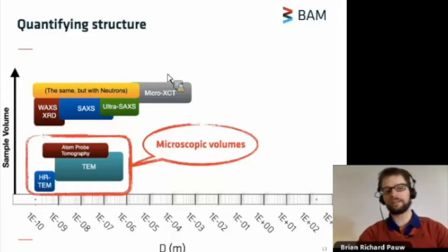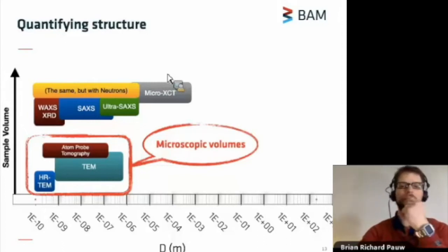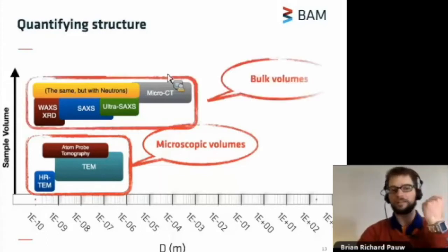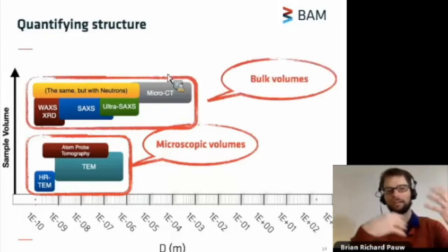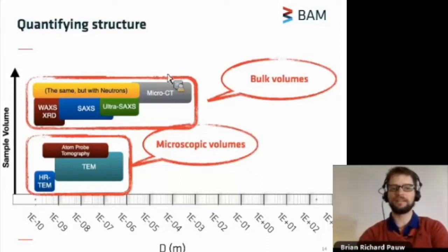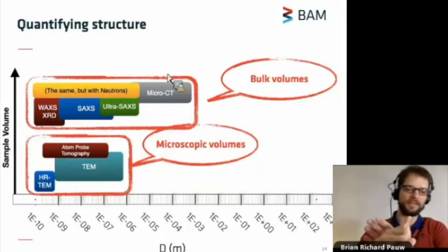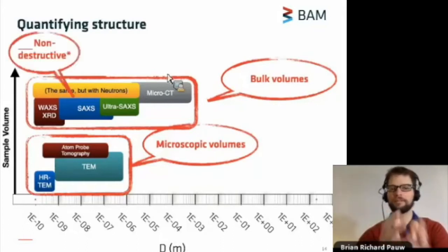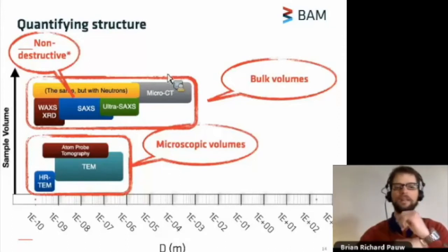But let's stick to the X-ray techniques for now. Big advantages are then that we're analyzing large amounts of material. We're getting a very good average over the structure there. And it is non-destructive. Of course, with an asterisk: if you shoot enough X-rays at your sample, you will change things. But in the laboratory, this is typically not a problem.